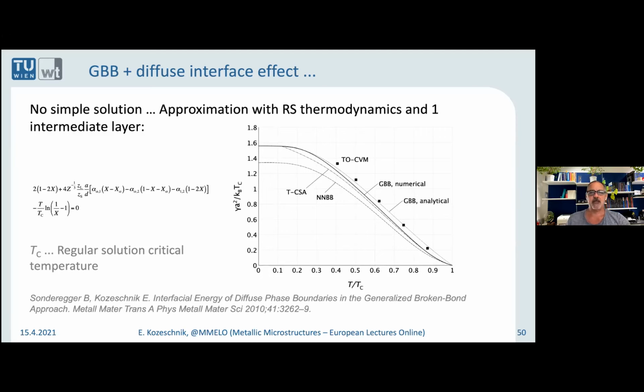The one approximation that we published also in this paper is the one where we said, okay, let's assume simple regular solution thermodynamics and only one intermediate layer. And for that, we could actually solve the problem. And we could solve the problem in terms of the so-called regular solution critical temperature, which is the highest temperature that you observe for a phase separation in the middle of the dome of the phase diagram.